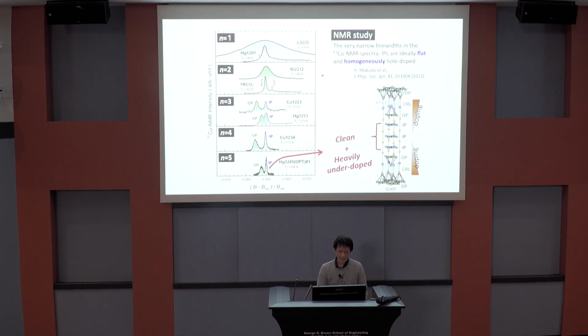So I keep saying the inner layer is very clean, which is more clearly described by the result of NMR. This is the spectrum of NMR, which is very sensitive to the roughness of the coupled layer and inhomogeneity of carriers. As you can see, LSCO has a very broad peak due to the buckling of the coupled layer, and bismuth 2212 is also very broad, consistent with the STM result showing an inhomogeneous state.